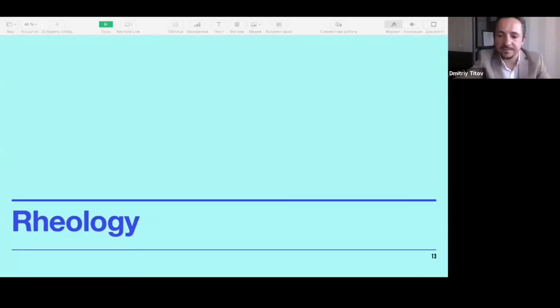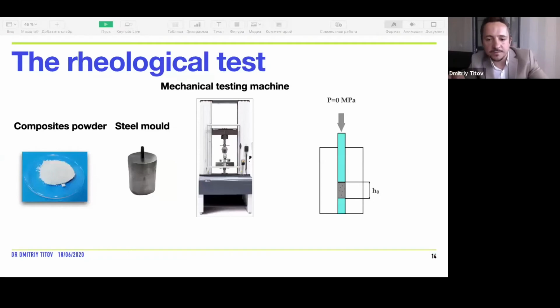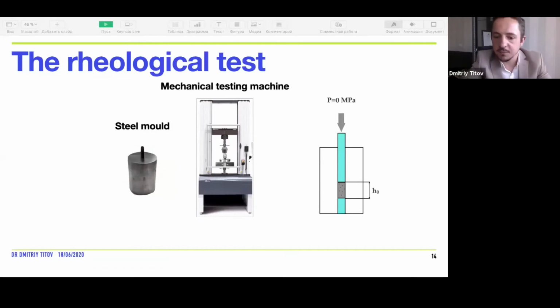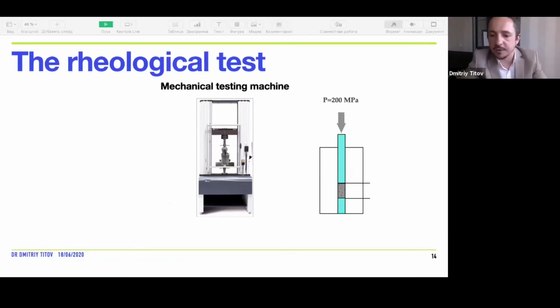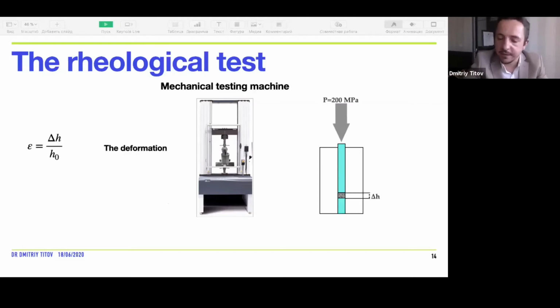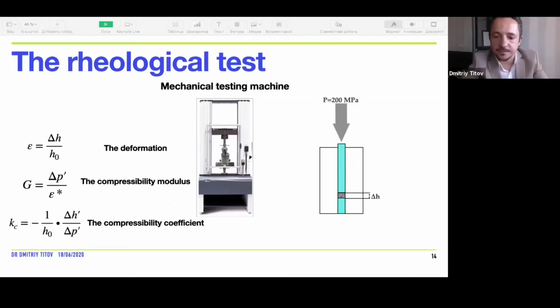And now about the rheology. The rheology properties were tested on the mechanical testing machine. At the beginning, we took an exact weight of the powder, placed it in the chamber. Then, on the mechanical testing machine, we conducted the experiment. At least 5 measurements were carried out for each composite. Then the values were averaged and calculations were made using the formulas of deformation, compressibility modulus, and compressibility coefficient.